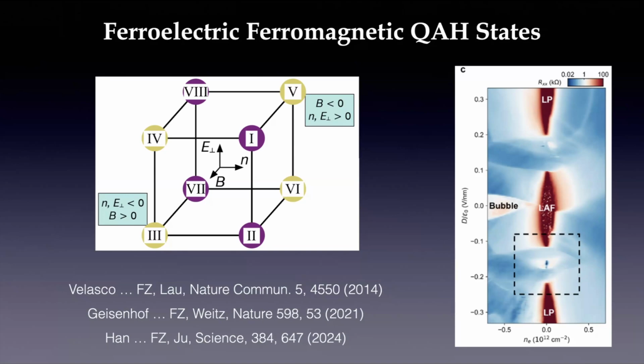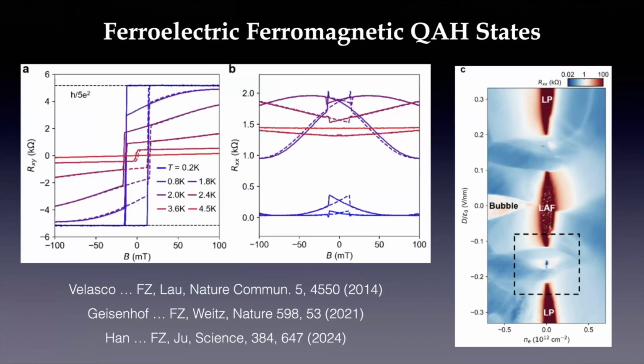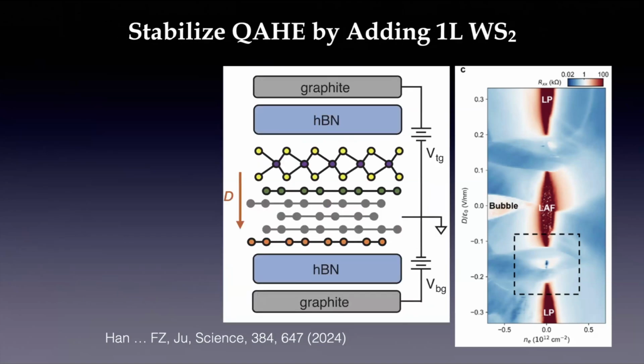It's a layer antiferromagnet phase, and if you add an electric field to the system, that layer-balanced state is going to be killed, and at a very large electric field, there's a fully layer polarized phase. In between there is this partially layer polarized phase. This phase turns out to have a Chern number of 5 because it's a 5-layer system. And this shows how good the quantization of the Hall resistance is in that system. It's fully quantized.